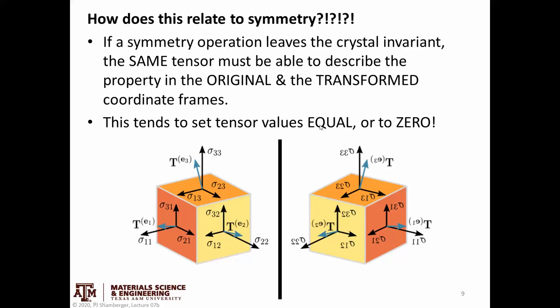And an extreme example would be a cubic system for a rank 2 tensor only has one independent parameter in it. So that's all we're going to talk about here.